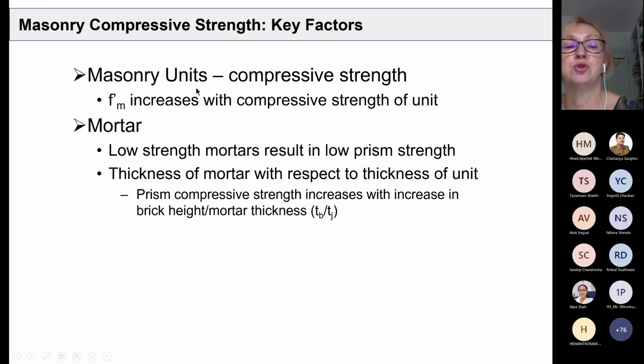So if compressive strength of masonry units is higher, we have stronger bricks. We are in northern India and we have 20 MPa bricks. F prime M is going to be higher than F prime M in Gujarat, where we have lower strength bricks and we use the same type of mortar. As far as mortar is concerned, lower strength mortar will result in low prism strength, but there is, I would say, a myth that mortar strength is important and the percentage of cement is more important than bricks. So that is not true. Actually, it's more important to have higher strength bricks.